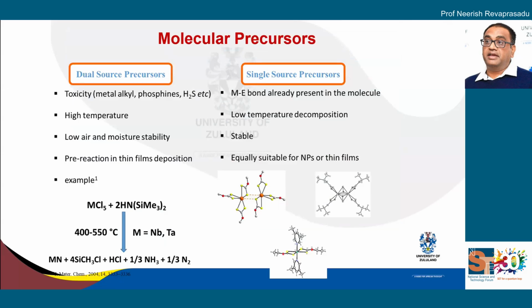So when we talk about precursors, we have what is known as dual source or a single source. So if you want to make a metal selenide, a metal chalcogenide material, you can take a metal salt and a chalcogenide source. So there are examples here. You can take a metal, tantalum or niobium, and your chalcogenide source can be something like a trimethylsilyl or bis(trimethylsilyl) complex, and you can heat them up. But you will see that you use very high temperatures. This is 400 to 550 degrees, and there are obviously some drawbacks, where the starting material is the metal alkyl, and it's very toxic. You're using high temperatures, low air and moisture stability, and there are problems with pre-reactions in thin film deposition.